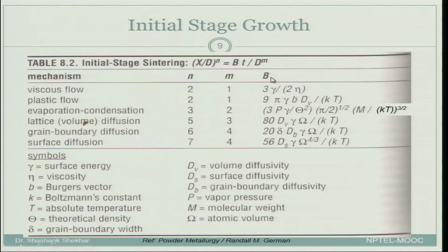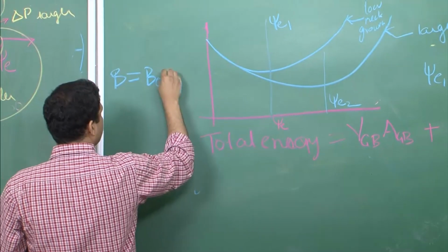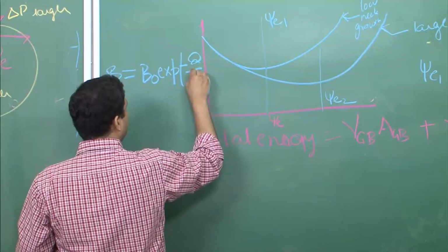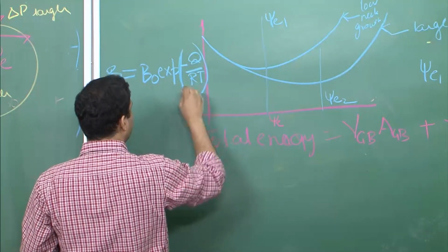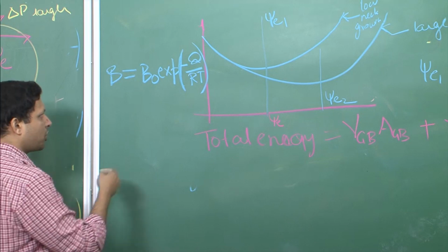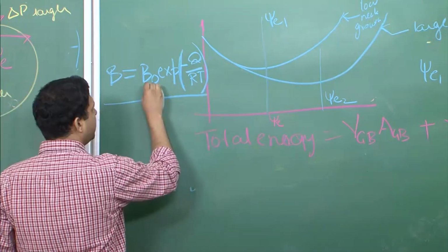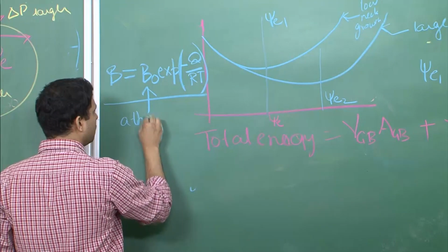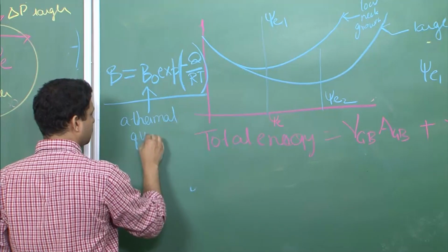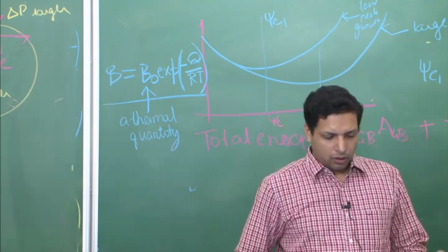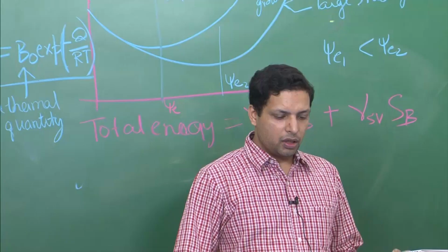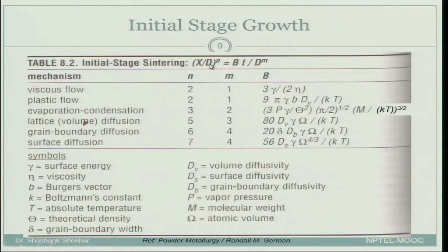Now, this B itself is actually a temperature dependent parameter. So, if you were to write it in terms of temperature, then it will look like this, where Q is the activation energy of the process through which this diffusion is, or this process is taking place, this densification is taking place, and here B naught will be your athermal quantity. This particular equation in general holds for values of x over d less than equal to 0.3. When the x over d value reaches 0.3, then we will say that initial stage growth has come to an end and we move on to the intermediate stage.